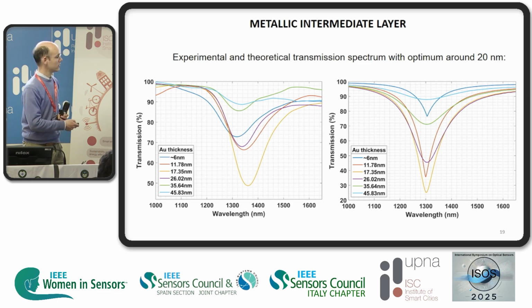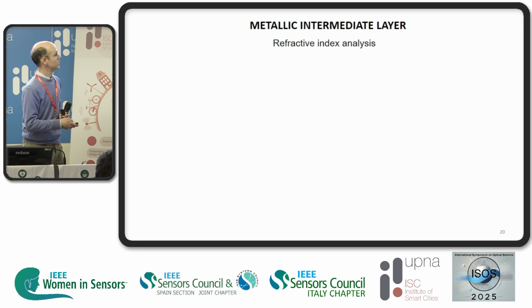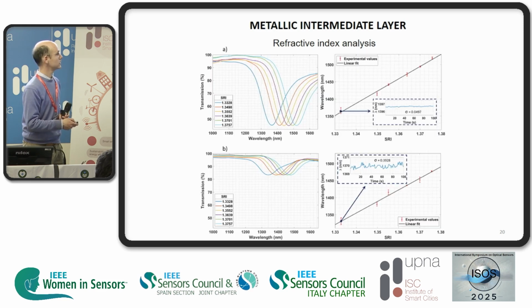So this is a quite important thing. Probably you don't see great improvement in terms of the width of the resonance, but obtaining a deeper resonance, we will see later, has some advantages. In terms of refractive index analysis, the deeper case is observed here as a function of refractive index. There is a wavelength shift to longer wavelengths, and the signal is quite stable. Here we analyze the noise. However, with this resonance that is less deep, the signal is more noisy.